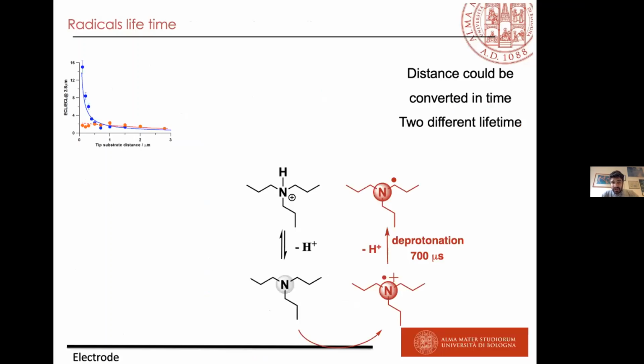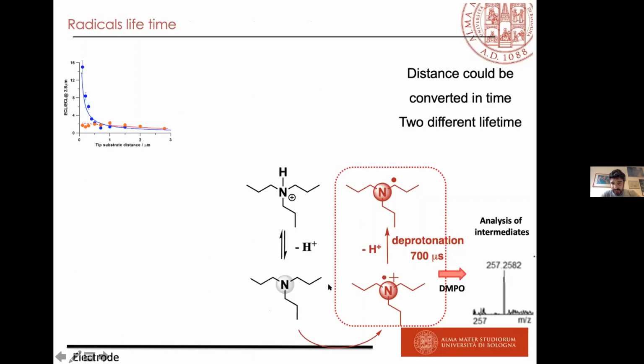Okay, so as I showed you before, this is the mechanism proposed by Bard and co-workers in his paper. In order to deeply understand what the mechanism was and why we have this discrepancy in close proximity of the electrode surface, we applied a potential for a long time, so we performed a prolonged electrolysis, and we used a classical radical trap to trap the electrogenerated radical.